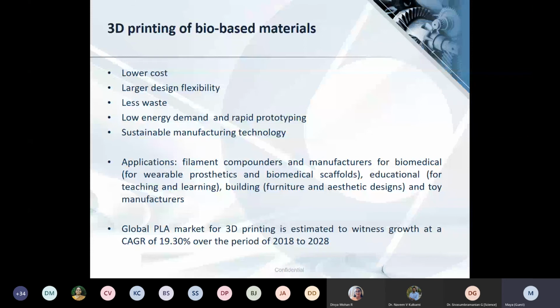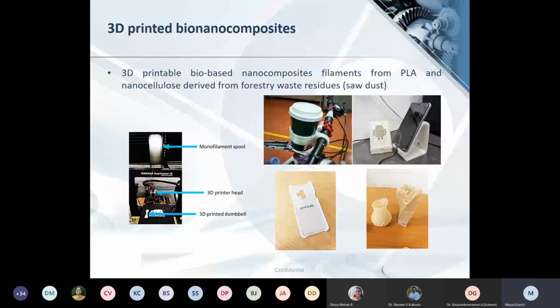And it is estimated that this market or this sector is going to witness huge growth over the next 10 years. So this is my PhD student's work. His starting material is actually sawdust, from where he extracts the cellulose nanofibers. And then the cellulose nanofiber is mixed with PLA in a twin screw extruder to get pellets. And then these pellets are drawn into filaments in another extruder. And these filaments are then used to 3D print a number of products, as you can see here.